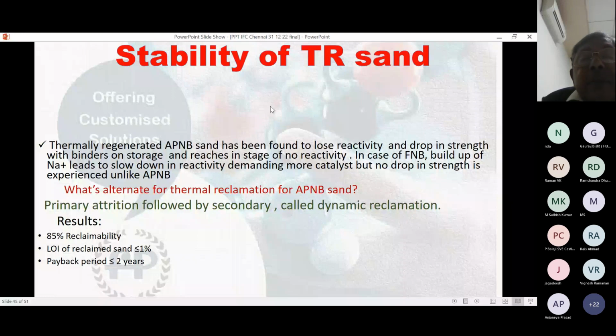What is the alternative to thermal reclamation of APNB sand in that case? Because 65% is no good and the maximum is 75%. So I have got a couple of examples. Primary attrition followed by secondary, called dynamic reclamation. Here, reclaimability is 85% assured, LOI of reclaimed sand is less than 1%, and the payback period reported in a particular foundry is less than 2 years.